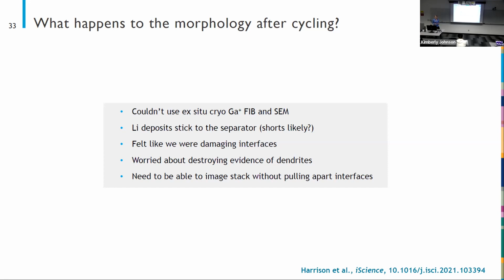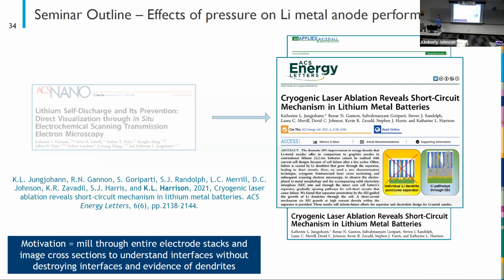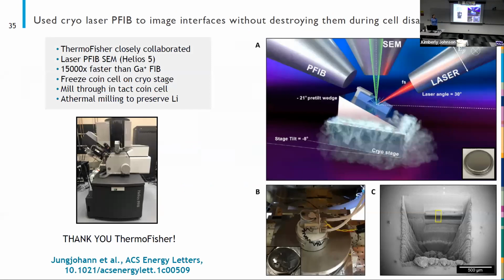This motivated us to try and figure out a way that we could mill through entire electrode stacks without having to pull them apart. That really isn't possible with gallium FIB because it's a very slow milling process, and we just really can't get through the number of microns we need to do that technique in this way. So my colleague, Katie Jungjohann, who's a microscopy expert that I work with a lot and has taken a lot of the images in this presentation, had this idea to try a different type of technique for this exact problem. And that led to the paper here, which I'll talk about a little bit. And then I'll come back to that study where we eventually were able to look at 50 cycles using this technique. But I want to explain first how we do it.